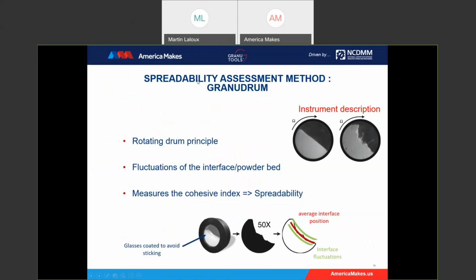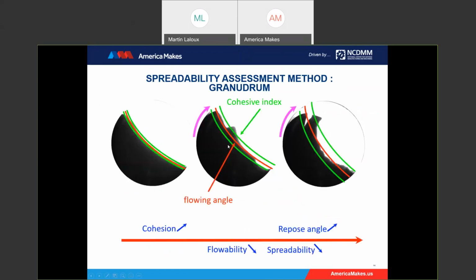To show you the assessment method we use here, the GranuDrum instrument. The description of this instrument is that we use the rotating drum principle. We rotate at different speeds from 2 to 60 or 70 RPM, and we look at the fluctuation of the interface of the powder bed. For each speed, we take 50 snapshots, we stack them, and we look at the average position and the fluctuation of the interface. To summarize, low fluctuation means low cohesion, so good spreadability. The more you increase the fluctuation, the more you increase the interaction between the particles, and the spreadability will decrease.